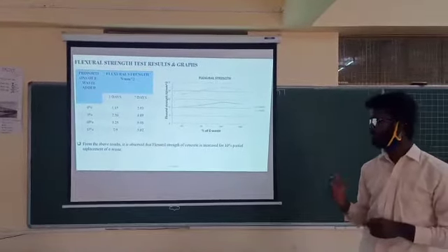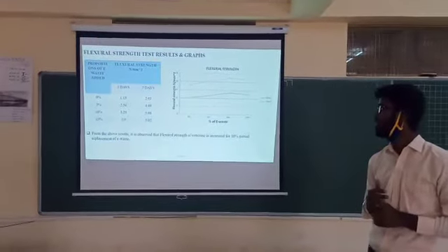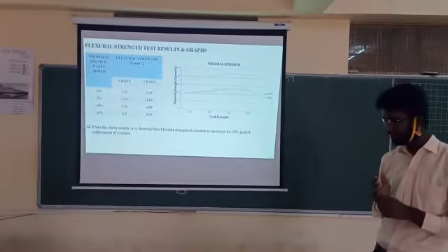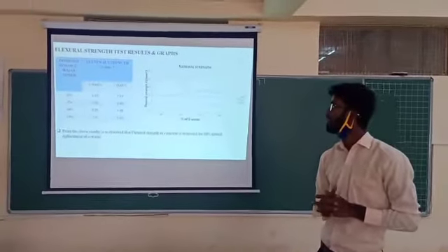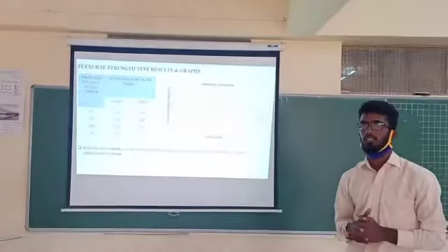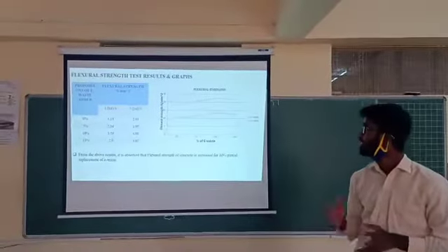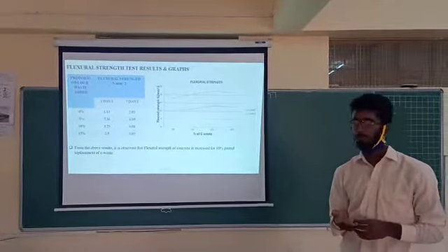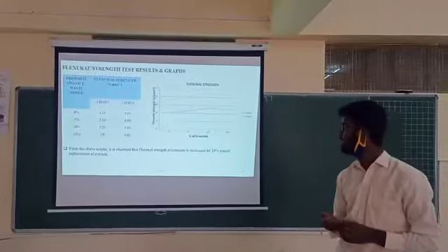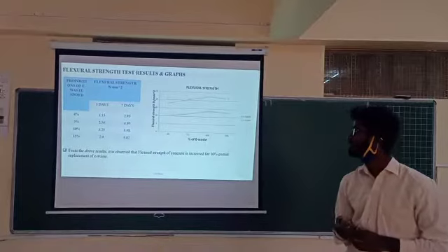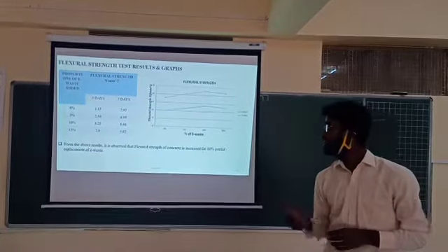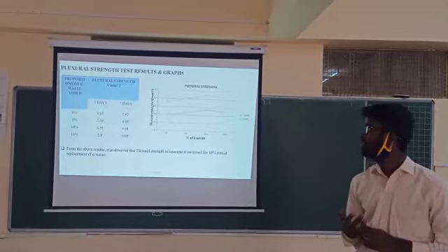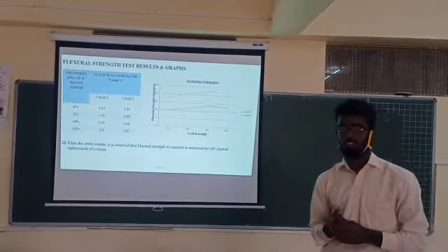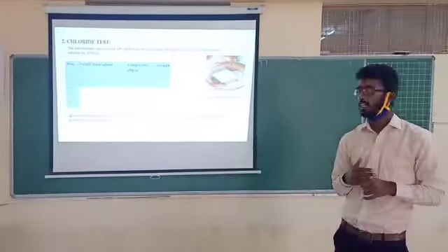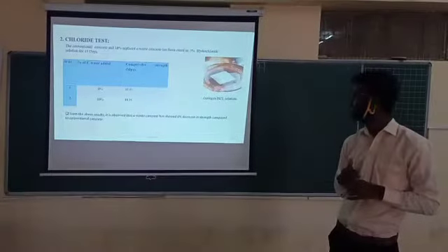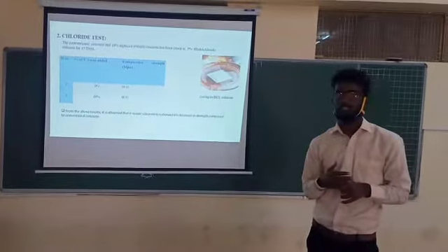In flexural strength also there is an increase. Flexural strength test result. From the above result, it is observed that flexural strength of the concrete is increasing at 10% partial replacement of e-waste, and 51% of strength has been increased when compared to the conventional concrete. From the above result, it is observed that concrete has shown 6% decrease in strength compared to the conventional concrete.